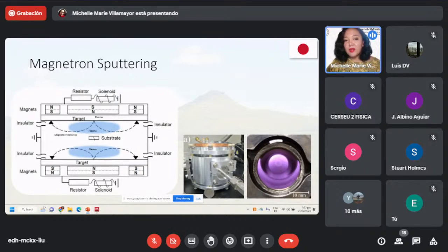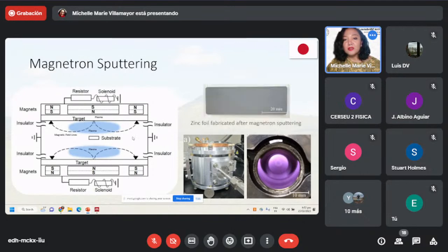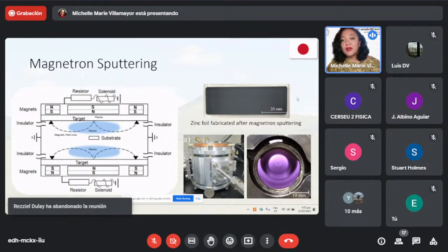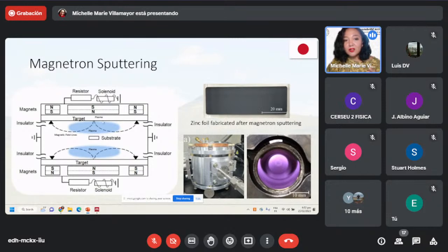Now, depending on the parameters, if the parameters are not correct, for example, if we introduce too little water vapor, then we end up depositing zinc on our substrate instead. So this is how it looks, because we did not introduce enough H2O. We ended up with a zinc foil, a highly opaque zinc foil on top of our glass substrate after magnetron sputtering. Now, if we are not careful, sometimes this zinc target will also get melted. And that is one problem that we have to deal with when doing experiments if we don't know the proper parameters.